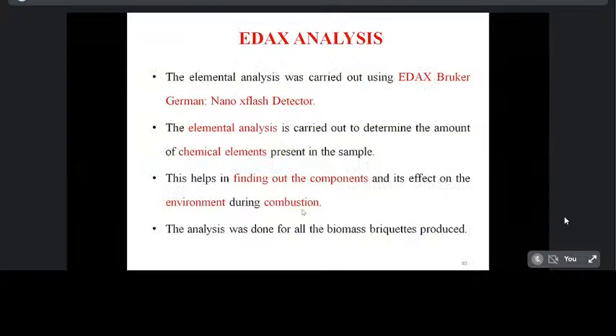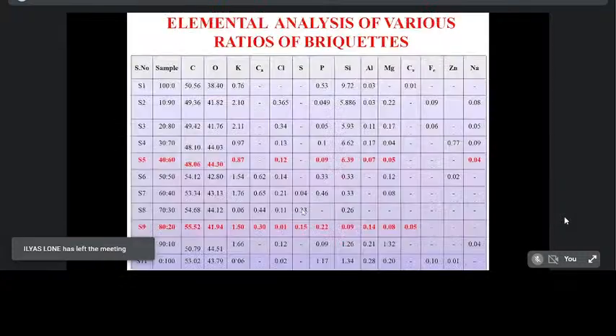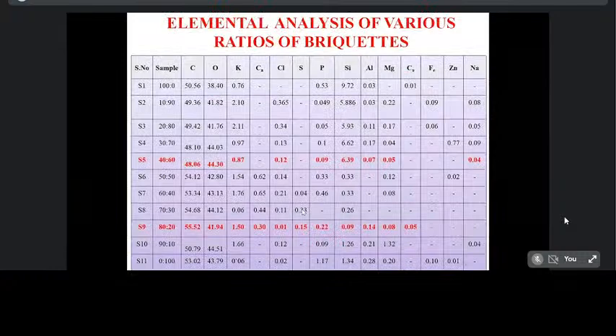The elemental analysis used an EDAX Bruker German Nano xflash Detector. This elemental analysis is used to determine the amount of chemicals, that means the micro and macro elements present in the particular biomass briquette. It also helps to find the components and their effects on the environment during combustion. This table shows the various elemental analyses of the produced biomass briquette. We have found nearly 14 elements: carbon, oxygen, potassium, calcium, chloride, sulfur, phosphate, silicon, aluminum, magnesium, copper, iron, zinc, and sodium.